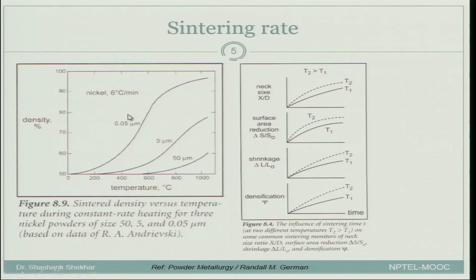So, when the particle size decreases, densification starts earlier and gets to completion at a much larger saturation value. Another thing you see here is that at the initial stage, the rate of change of density with temperature is much larger, and with time it decreases. Again, that is related to neck growth. Here initial necks must have formed, most of the particles have initial necks. So, the neck radius is very small, and therefore you see a much larger growth, and as the neck size becomes larger and larger, the growth rate or the sintering rate reduces.